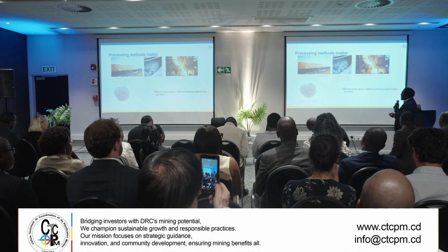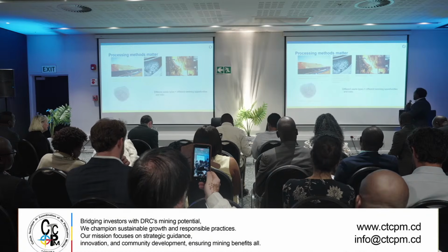So the kind of waste one would generate also depends on the ore processing. If one is processing their ore through heap leaching, what you end up having at the end is a coarse residue and very large pads of material. When you do flotation, I previously showed the tailing dams, so that's usually what you end up having. When you do pyrometallurgy, you end up with a slag, and then with refining, you have either slime or sludge. So all these different wastes represent different remining opportunities, but also different kinds of risks.